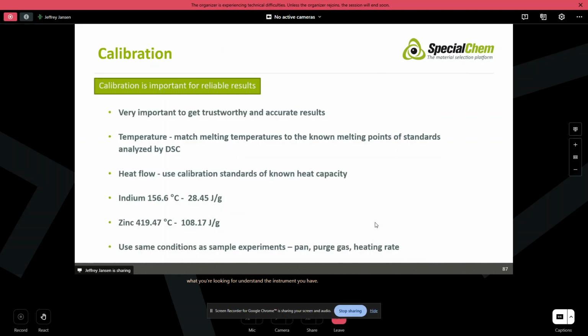Calibration, very, very important. You want to get trustworthy, accurate results. That means you need good calibration. You need to calibrate both temperature, so what the temperatures are, as well as the heat flow. Okay, so typically for temperature calibration, I like to see 3 temperatures.